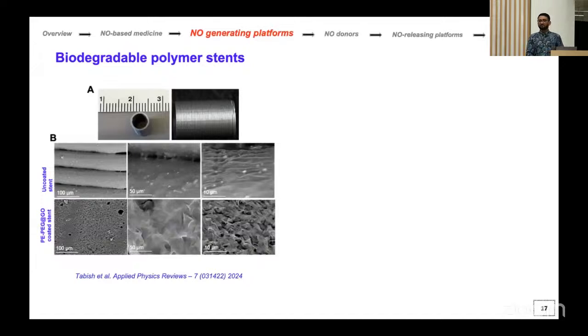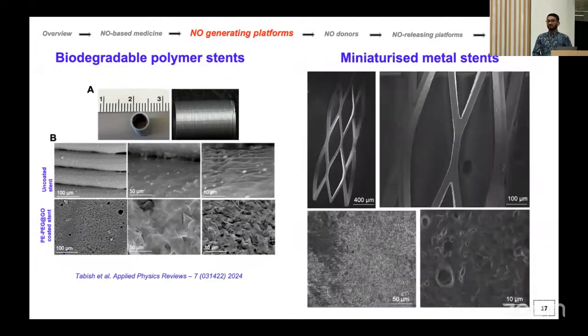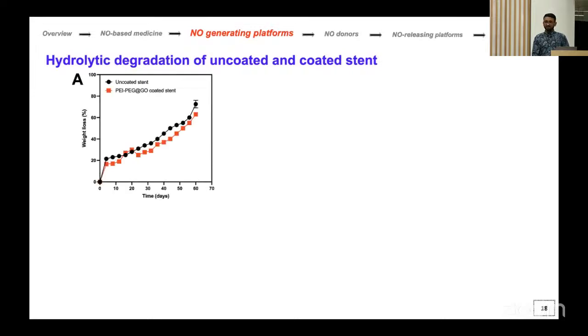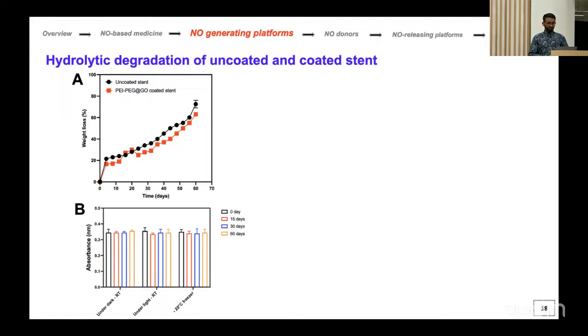And then we coated these materials onto biodegradable stents to see whether graphene has been successfully conjugated onto the stent. But because recently there has been a lot of controversy around biodegradable stents in cardiovascular diseases, we also used it on bare metal stents to show that our coating system is feasible and can be used on different cardiovascular implants. From scanning electron microscopy, we can clearly see the sheet-like structure of graphene. And then we also looked at the hydrolytic degradation of coated and uncoated biodegradable stents to see whether the coating affects degradation, which it doesn't, up to 60 days under accelerated conditions.